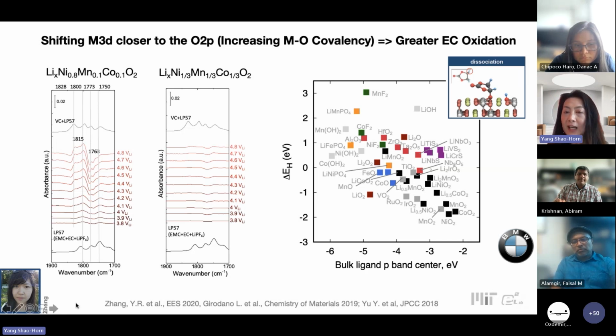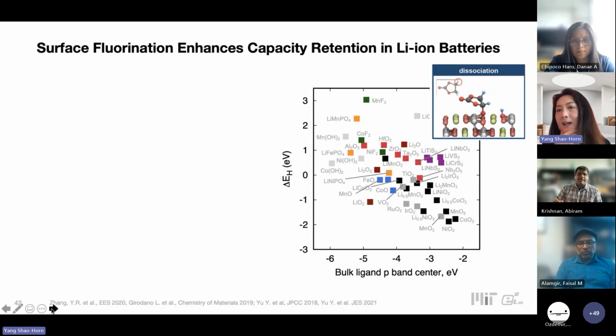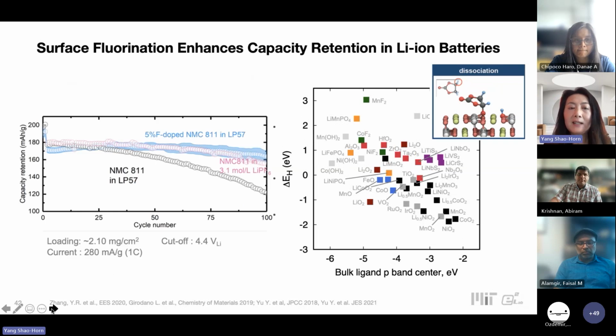And this can be utilized to explain the phenomena in the literature, what surfaces people have used and found success, as well as to predict new surfaces to develop a more surface-stable NMC or nickel-rich compound. And utilizing this design principle, we can coat a surface with a little bit of fluorine that can lead to a diminishing of degradation of NMC 811 in a conventional electrolyte. So this is tuning of the surfaces so that we essentially prevent the oxygen site from activating the CH bond of the carbonate, right? And to prevent degradation and generation of a protic species.